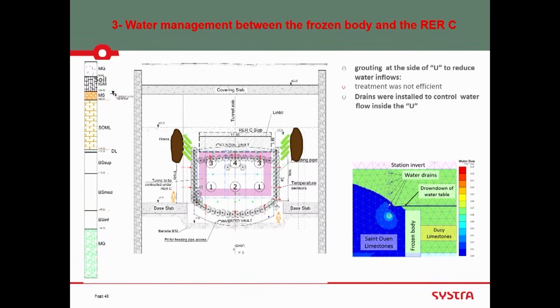There was a grouting which was done in this highly pervious area, but unfortunately, it didn't work. Because, as I said, when you try to grout with a cover of 2 meters, 3 meters below the slab, nobody wants to put a lot of pressure, and the grouting pressure was 200 kPa. So with 200 kPa of grouting pressure, due to the presence of the base slab, you grout nothing. And we got, at the end, water coming. So we were obliged to do something.